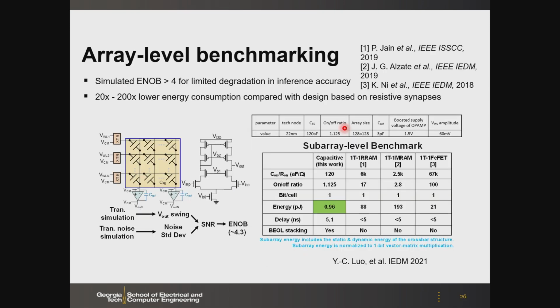And then we further did some benchmarking. Let's say if we scale up the system, right, because we only have an 8 by 8 or 10 by 10 small array in the experimental setup. But if we scale up to 128 by 128 by simulation, then we can demonstrate that the energy to do this kind of charge domain computation, compared to the resistive counterpart, is much lower, like 20 to 200 times lower compared to other competing technologies. So of course, the limitation of this one is we have to consider the thermal noise, because if a system is full of capacitance, it suffers from the thermal noise.